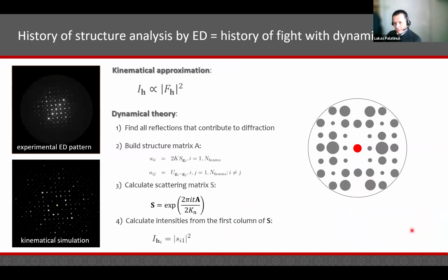As I mentioned, the consequence of having strong interactions of electrons with crystals is that we face so-called dynamical diffraction effects or multiple scattering effects, dynamical diffraction. On this slide, I outline just the basic principles or basic difference to the established kinematical approximation.